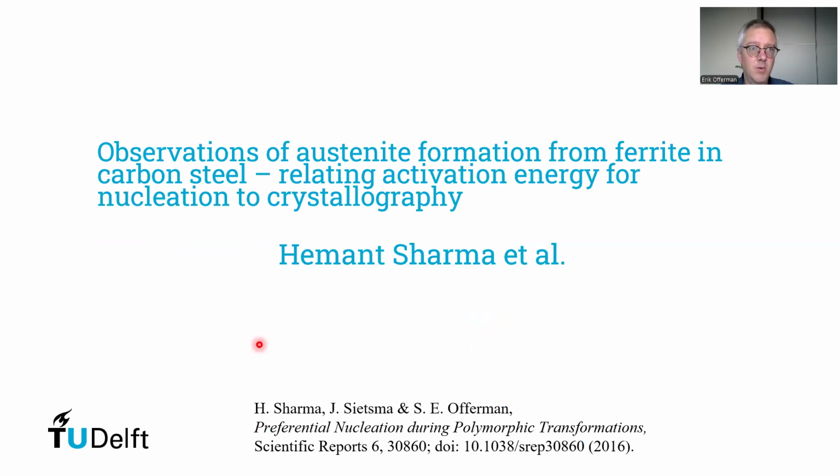Okay, so now we know that special crystallographic orientation relations play an important role in the nucleation, but we have not in one experiment correlated the crystallography to the activation energy for nucleation. And there could be some intervening variables that play a role, and I can already tell, the strain energy also plays an important role during the nucleation.